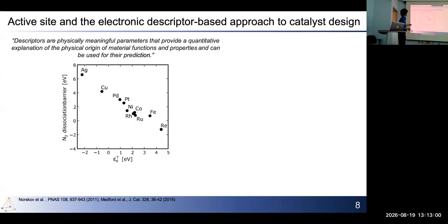The trend shown here is that as the D-band center moves up relative to the Fermi level, your adsorption becomes stronger and stronger. So if you want a catalyst that really strongly adsorbs nitrogen, you choose something like rhenium here.